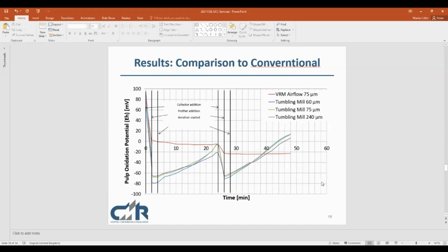What this is coming down to, and apologies guys, this is now we're going into flotation here. This comes down to the lower oxidation pulp potential for the tumbling mill products, which is affecting the xanthate adsorption onto the surfaces there. So it's your 3 lower figures here. It's your ball mill products versus just one vertical roller mill product here. So significantly higher oxidative potential. And again, just highlighting the consideration that needs to take place when comparing vertical roller mill or any dry grinding products to that for conventional wet milling systems.